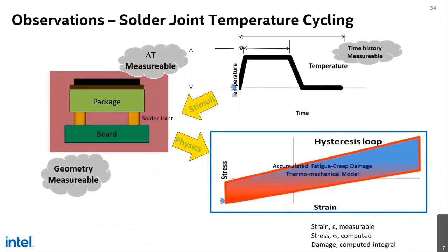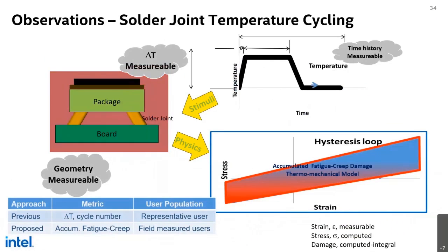Okay, and that's something that we can do. So previously, you know, we can use a Coffin-Manson equation and think that we're doing reliability, but we're really not. The best thing to use is the cumulative peak, creep, and fatigue damage model, and this can allow you to essentially do predictions at various use conditions and different geometries rather than the one geometry that you've been testing all the time, which we're changing geometries every day. So we need to do this.